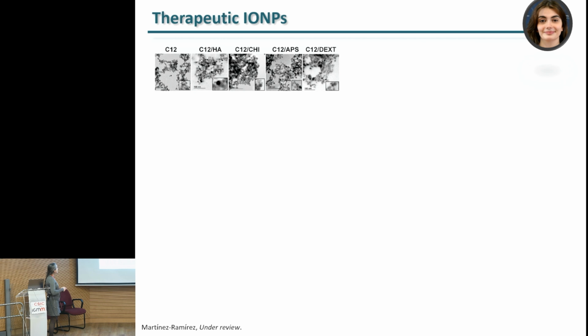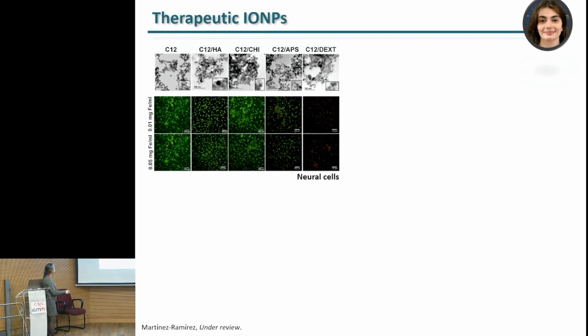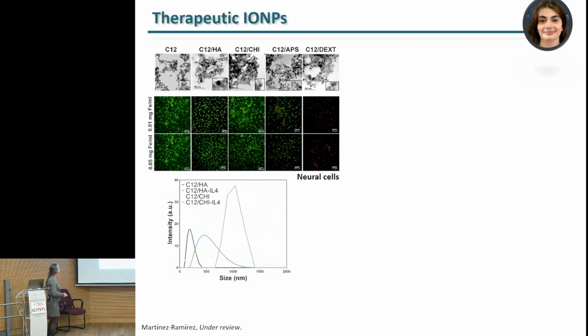We found very interesting and promising data also for the in vivo implantation. And more recently, what she has done for the project is she also tested some other coatings, as you can see here, not these biomolecules, but other, this is also a biomolecule, this APS. So different coatings just to make different options of coatings for loading, and tested the biocompatibility. Unfortunately, these two were discarded, as you can see here, because of the bad neural response. So we confirm that these chitosan and hyaluronic acid were really the ones giving us the better response.